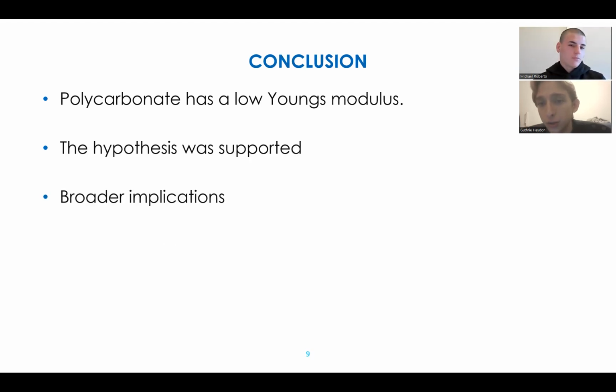So overall, in our conclusion, we concluded that polycarbonate has a low Young's modulus. This is seen by our calculated values of the strain of the polycarbonate and their percent errors. We can notice that when using the radii in class, the foam radii, for our theoretical and experimental strain, the percent error is a little bit greater than 30 on our smallest percent error. But what's really interesting about that is that since it's a very small strain, in the grand scheme of things, it's pretty accurate compared to the theoretical strain, which is quite interesting.